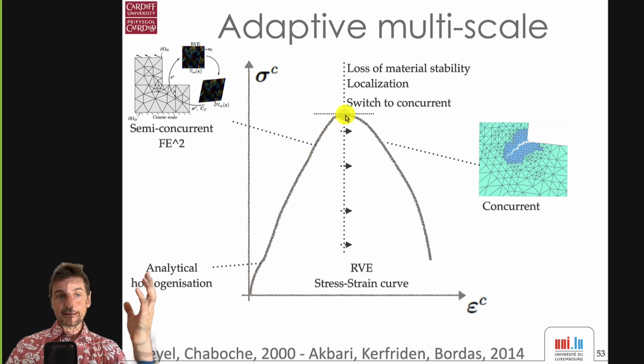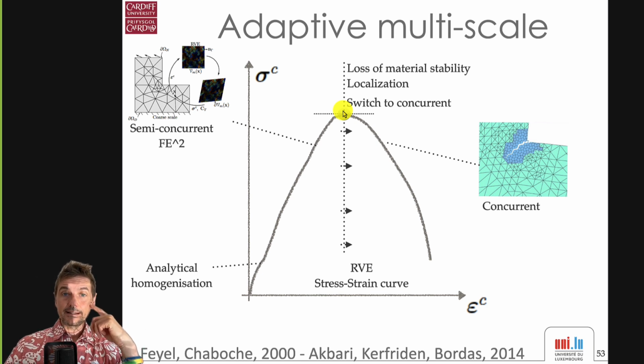And when we reach the peak, this whole semi-concurrent approach goes out the window, because in fact we lose separation of scales. The reason why we lose separation of scales, which is also quite difficult to understand from the literature, and I think the best person in my team to talk about this would be Lars Bakes, who worked on the quasi-continuum method and is very knowledgeable in this.